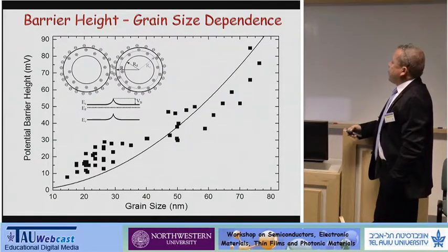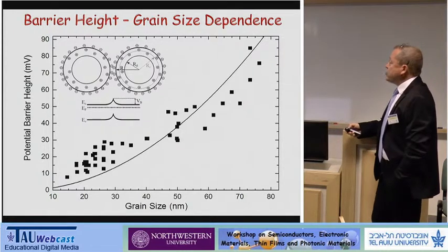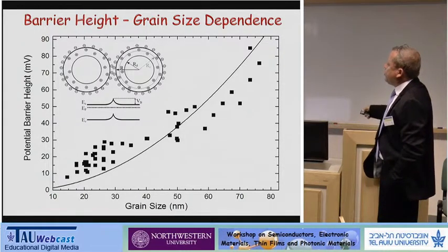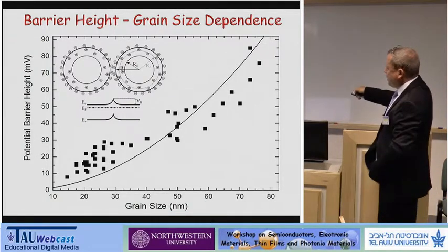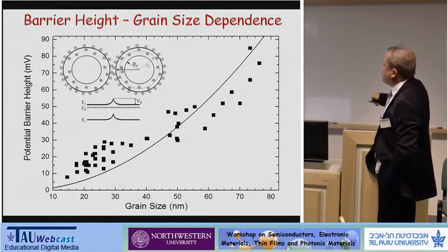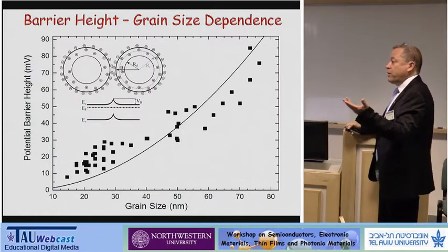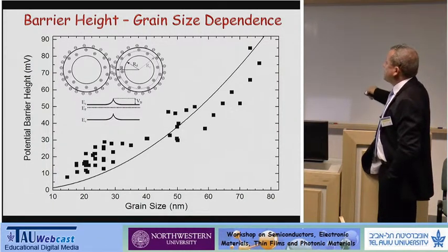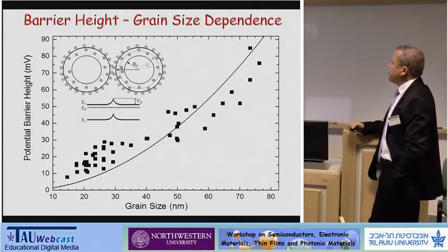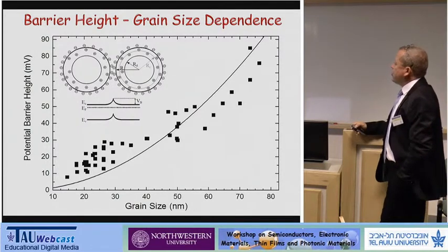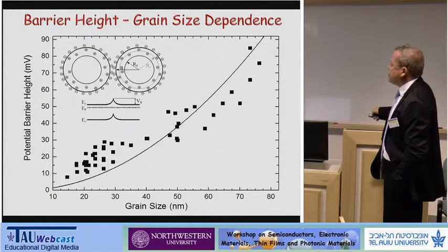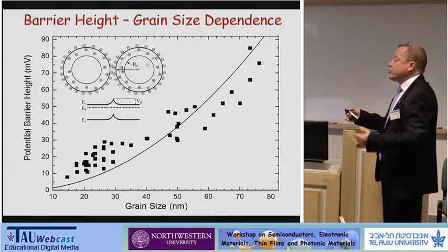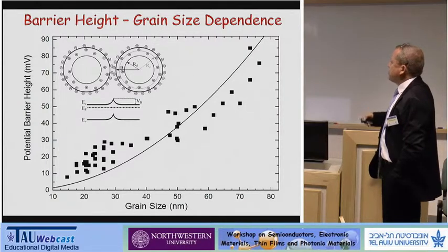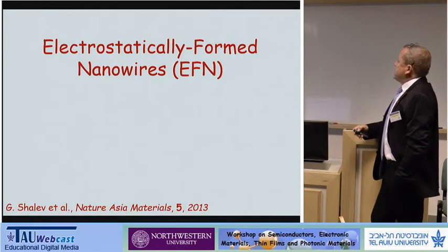And in the end, after measuring many, many grain boundaries and many, many grains, we came out with the statistics of the potential barrier height of the grain boundary. This is the potential height between 2 grains as a function of the grain size. By measuring many, many grains and solving the Poisson equation, we came out with these statistics, and this is an analytical solution to the 3-dimensional Poisson equation. You see that it agrees fairly well with the measurements. So as you see, as the grains become very small, as expected, because you don't have a space charge region, the barrier height becomes very, very small. So this is the first part of the talk.